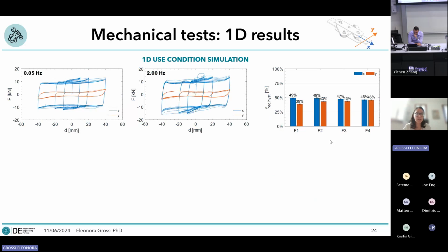Here you see the result of the monodirectional test. In here you see the hysteresis cycles. The blue lines are associated with the longitudinal direction and the orange lines with the transversal direction. You can have a little reminder up on the top right of the slide. You can see that the hysteresis cycles obtained at a smaller frequency and high frequency are quite similar, and this is quite important because the device can act in the same way independently from the frequency content of an earthquake.